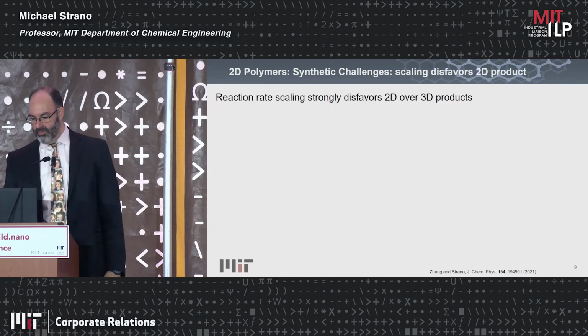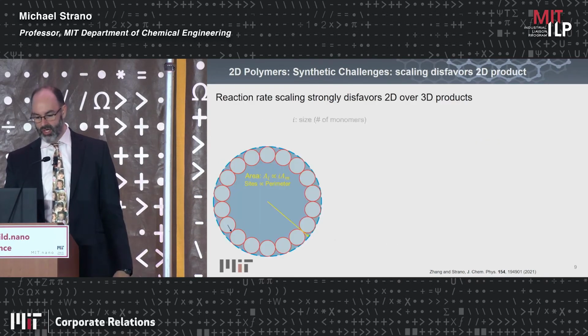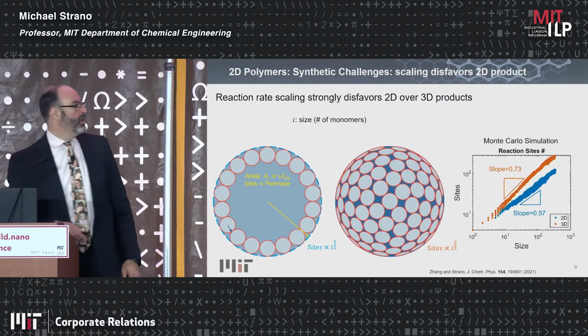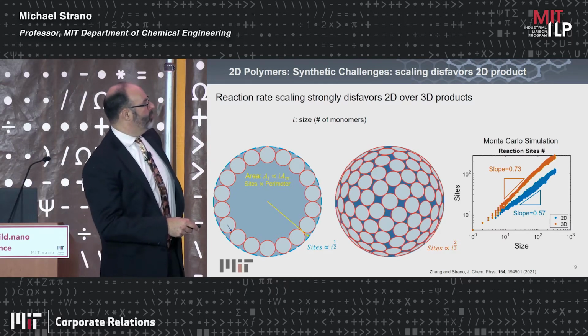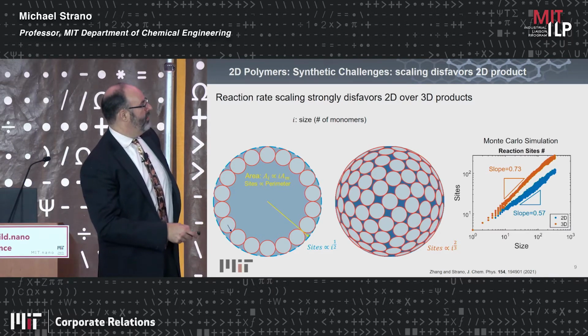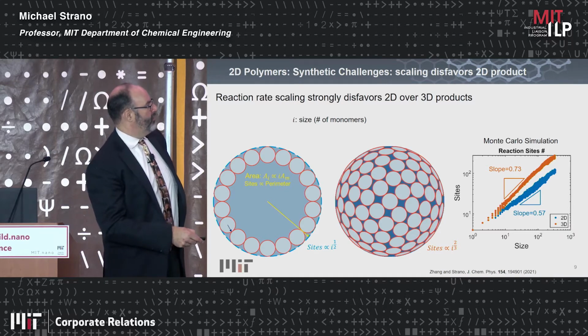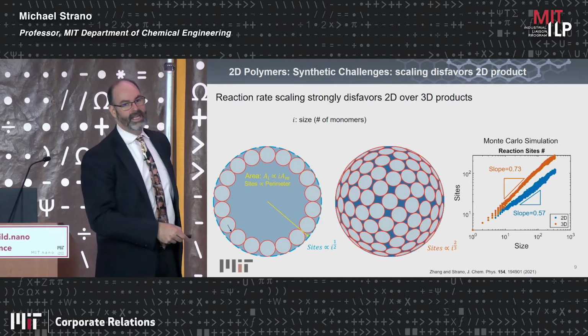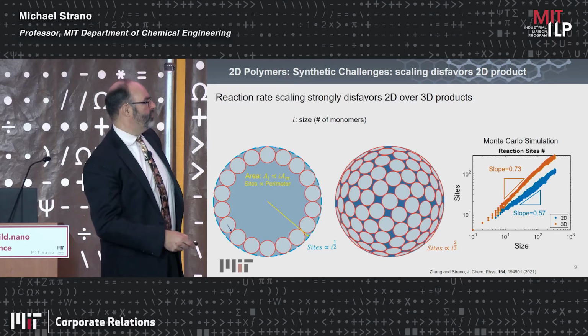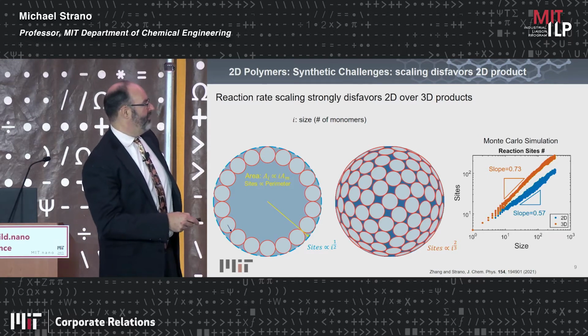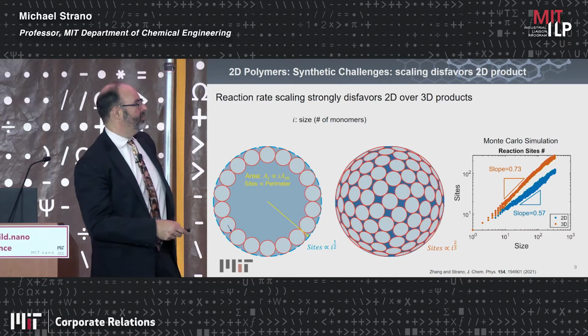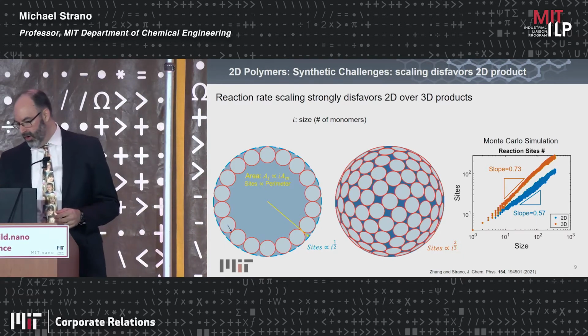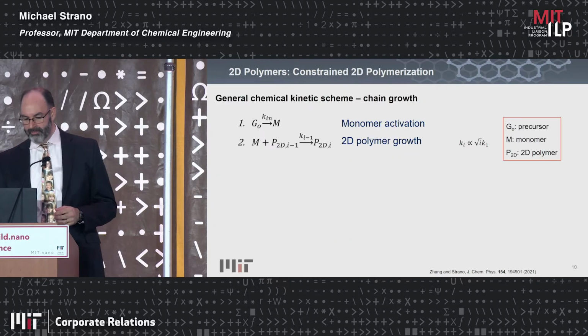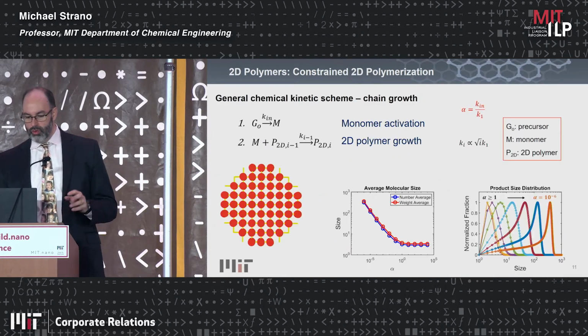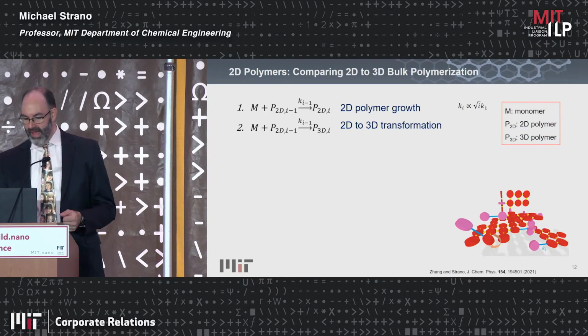And that's a problem because it's just basic geometry to show that you will always grow. There's more sites on a sphere than there are on a disk. And so it's a very depressing result. It means for any chemistry, you'll always grow in this 3-dimensional amorphous blob, faster, much faster than you will a disk. So this is essentially game over. There is, I'll spare you a lot of the math and our theory.